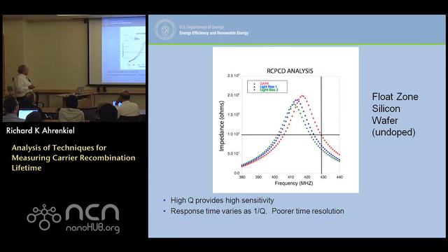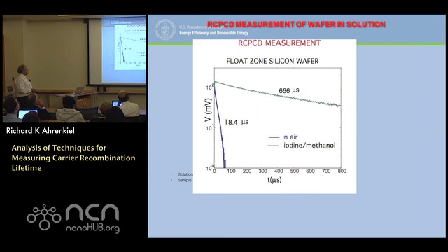Now, the higher the Q, the sharper the slope, the more it would change. But the penalty for increasing the Q is the response time varies as 1 over Q. So with the Qs I have here of 30 or 40, the response time is 20 or 30 microseconds. Now I could have a Q of 1,000, but the response time would be a microsecond. So it's a trade-off between sensitivity and response time. So it's basically coupling the conductivity of the sample, which is increasing with light bias, and that causes a change in the impedance of the entire circuit. So it's really like FM modulation in effect. We change the resonant frequency with conductivity of the sample. So in a transient measurement, we sit at one particular frequency, and then the light pulse comes on, and then the excess carriers are generated, and then the decay.